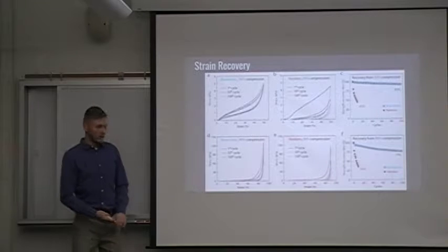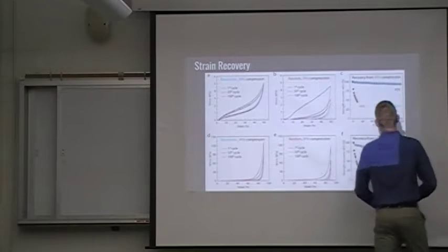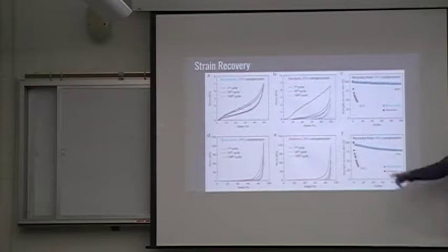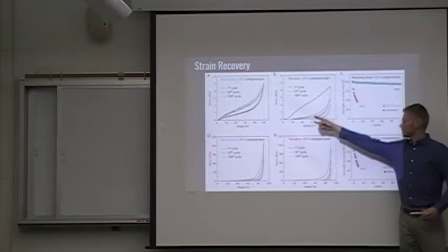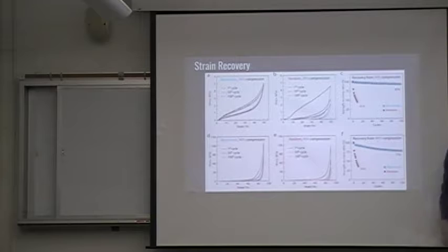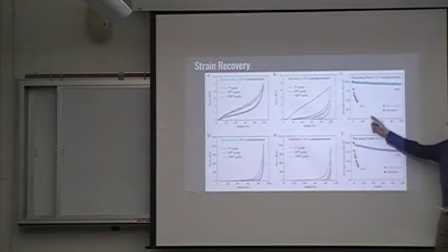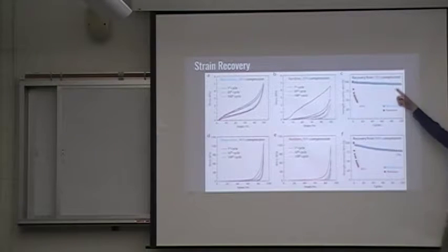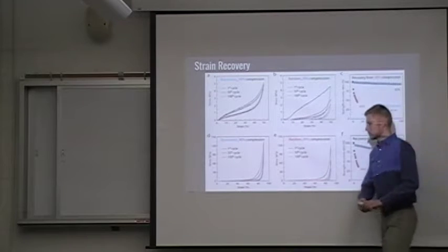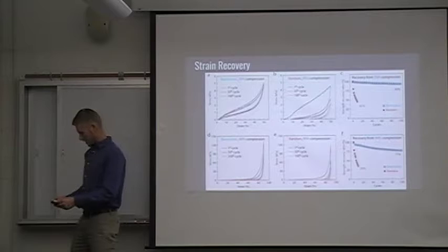And notice how on this graph, you see that the random, which is outlined here, that is biomimetic, the random is the red, and it does not recover nearly as well as the graphene aerogel does, even after 100. And here, they both start at the same place, so they're both just as thick, but the random breaks down.